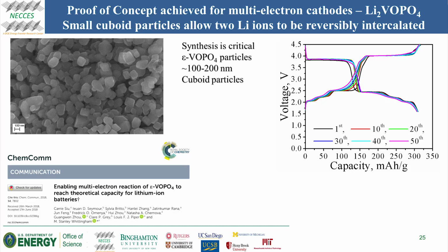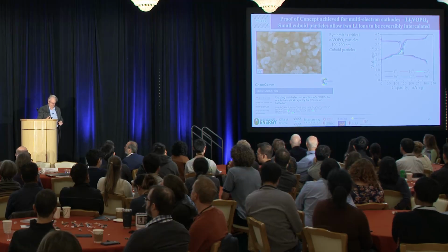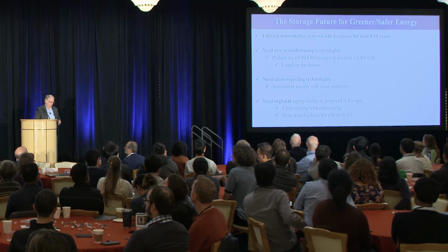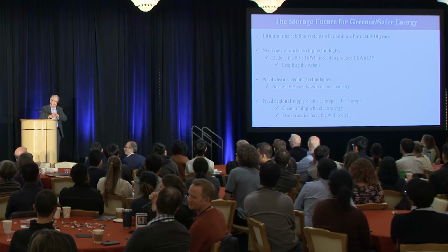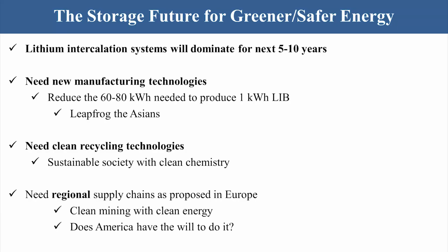Challenges today are to stop these materials reacting with the organic solvents. These vanadium phosphates are commercially known oxidation catalysts, so we have to moderate their reactivity, but the material itself seems to last forever. I'm getting a bit off the science now and a bit more into the needs. So these intercalation systems we've worked on are now exactly 50 years old. We don't anticipate anything else knocking them off their pedestal for at least, I would say, the next 5 to 10 years. Any new system has got to come in with better economics, and that's going to be very difficult when you're making billions of cells with lithium ion.